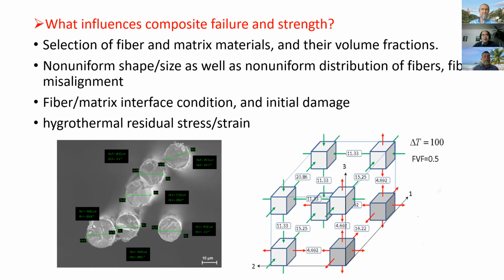So this one shows that in a simple analytical unidirectional model, when you have a fiber and matrix with 50% fiber volume fraction and a temperature change of 100 degrees, then this example showed that the fiber is subject to tensile stress, and the matrix is subject to compressive stress, and the stress is also going to be different depending on the orientation. So definitely those thermal residual stresses are going to affect the failure of composite. And even Tony mentioned that if you have the layered composite, then each layer constrains the others, so there is going to be additional residual stress during the fabrication process. So all those parameters are going to affect the eventual failure of composite strength.